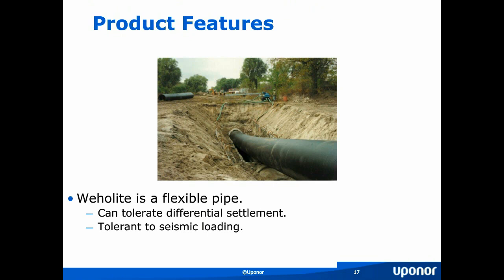The other feature of Weholite pipe is that it's a flexible pipe. It can tolerate differential settlement very well. We have a facility in the Tsawwassen area whereby they chose Weholite pipe because in that particular location they were going to experience high degrees of settlement. And also Tsawwassen is very close to Vancouver, which is in a seismic loading area. And they also wanted a pipe that's going to stand up to seismic loadings. And so for that reason, they chose Weholite pipe for that particular project.